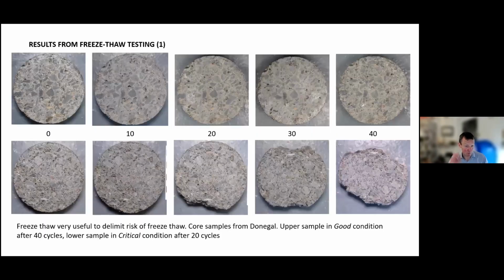So here's results from two Donegal cores. You can see 0, 10, 20, 30, 40 cycles. The upper core remains in good condition after 40 cycles, whereas the lower core is actually falling apart in 20 cycles. It's in critical condition. You could easily break that with your hand at that stage. And this is interesting because it's showing us information that we may not have picked up on by any of the test suite A or B or SEM analysis.